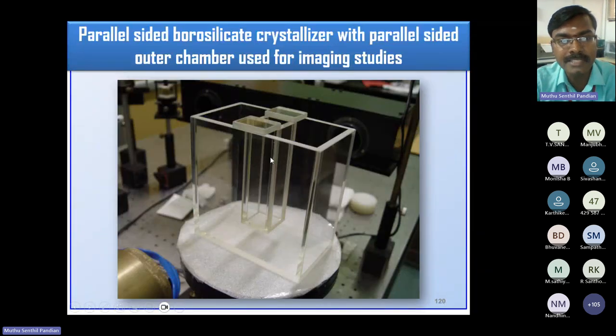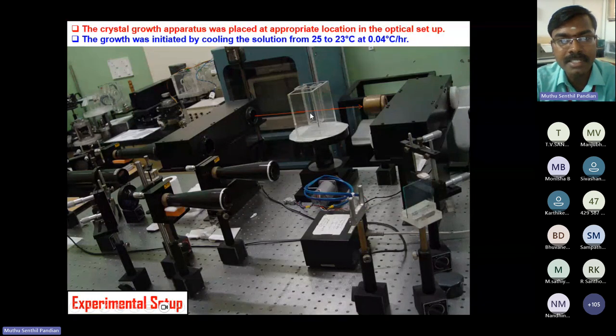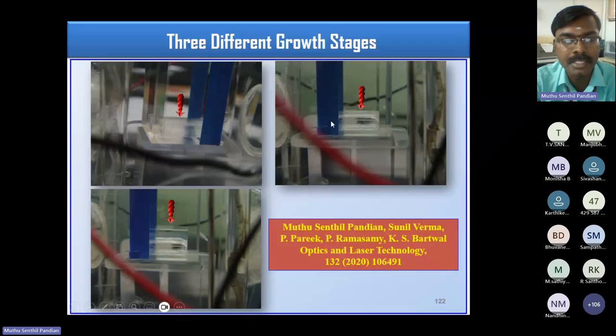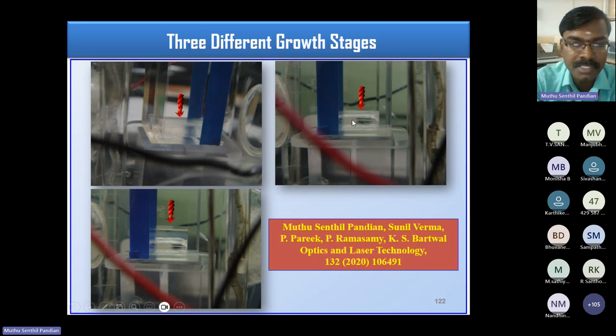So this is the actual experimental setup we have used for the imaging technique. We mount the seed crystal at the bottom of this borosilicate glass sample, and we pour in the solution, and we carried out the imaging technique. So this is step one, and this is step two: we mount the benzophenone single crystal at the bottom of the glass sample along its A direction, the 100 direction, and pour the benzophenone solution inside the borosilicate glass sample. You see, this is the mounted seed crystal, and the roughness has started, and the transparent portion has started. We capture the image between the crystal and the solution interface.